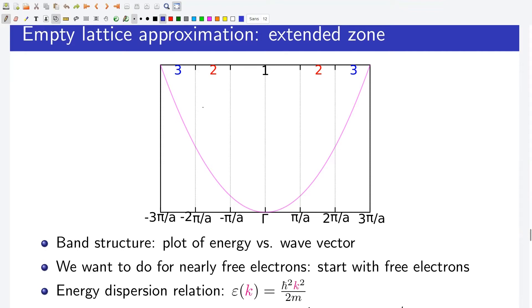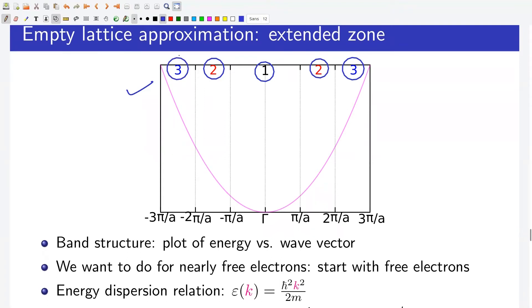I show the free electron energy versus k parabola in the case of 1D. The plot of energy versus wave vector k is known as the band structure. Zone one denotes the first Brillouin zone, zone two denotes the second Brillouin zone, and zone three denotes the third Brillouin zone. This is known as the empty lattice approximation: although there is no potential, we still assume there is some underlying lattice and reciprocal lattice, since we want to ultimately understand the band structure of nearly free electrons.